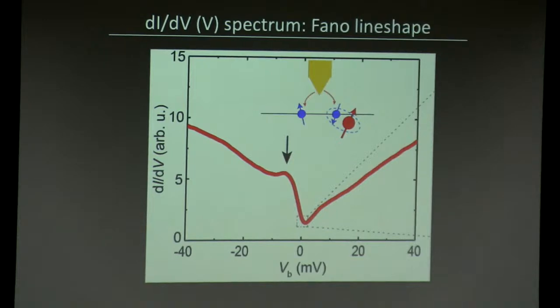We actually know what this line shape is. This is called a Fano resonance, and it's due to a sort of interference process. It's a result of the tunneling process. In reality, there's actually a sharp peak in the density of states in the sample, but when you tunnel in, you can either tunnel into the localized state or the continuum that exists. These two processes can interfere with one another and end up in this very strange line shape called the Fano line shape. Anytime you see a Fano line shape, you should immediately translate that into the existence of a peak in the density of states right there.